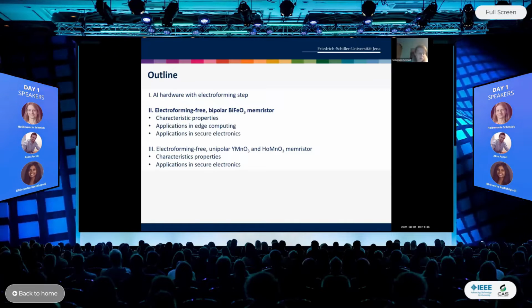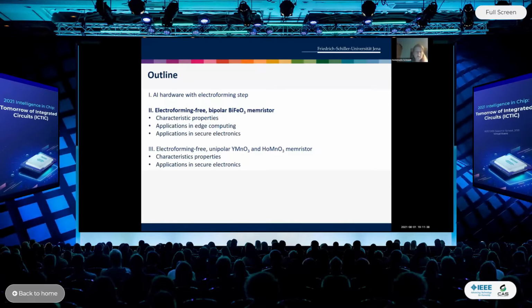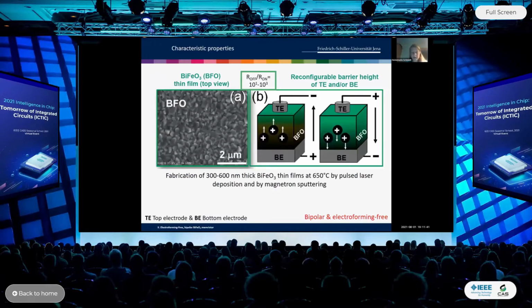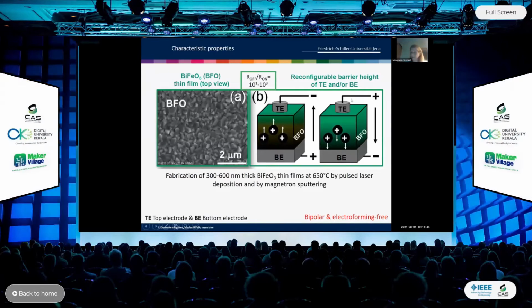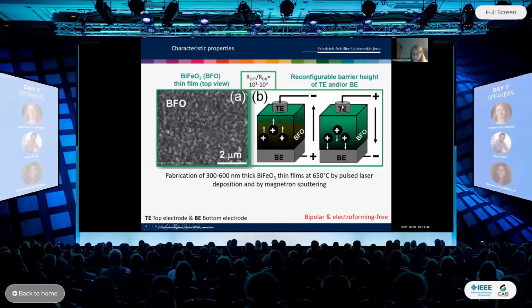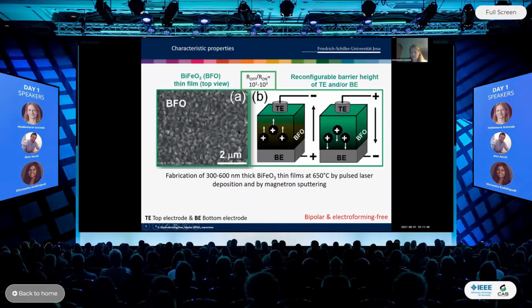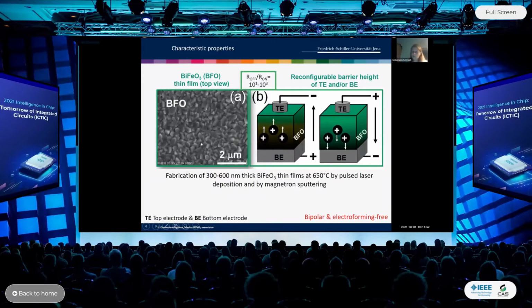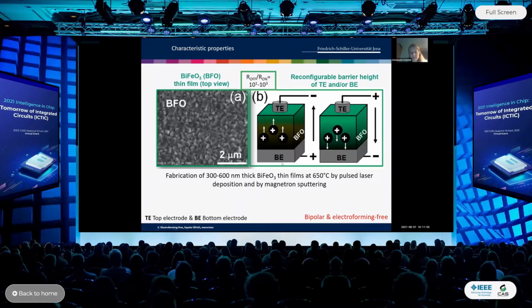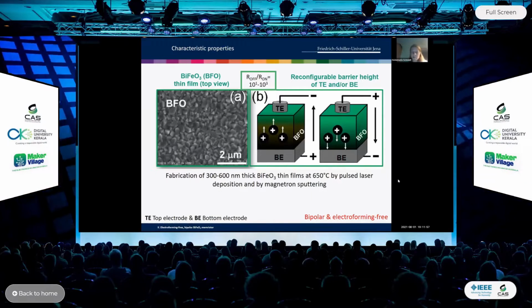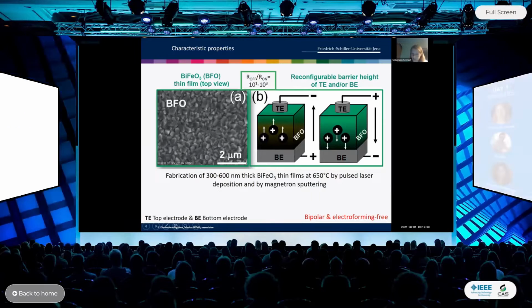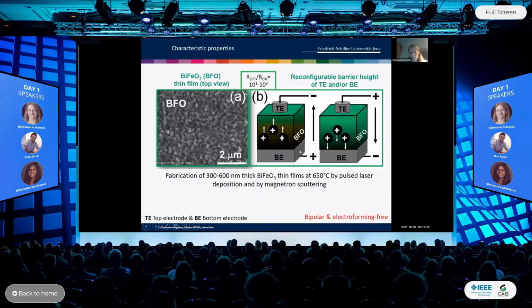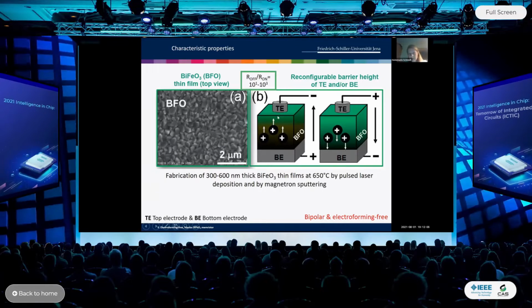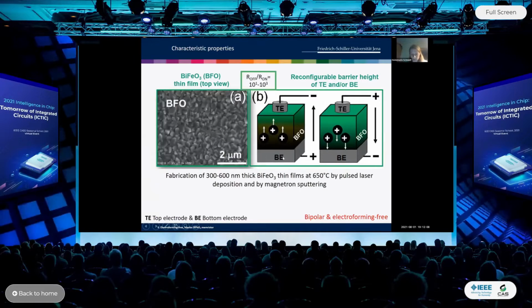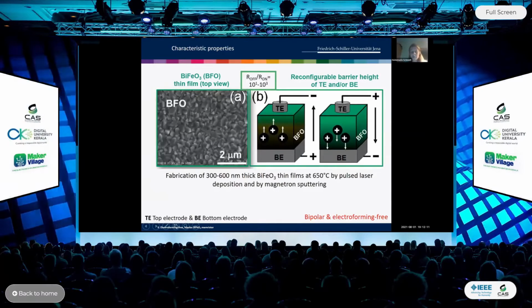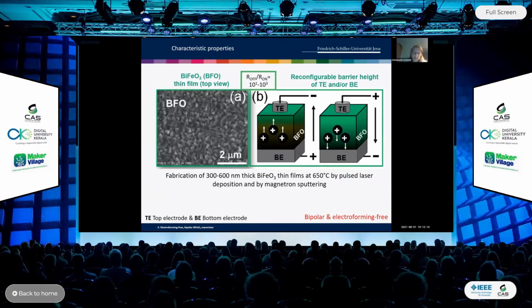And this brings us to the first example of the first part, electroforming-free memristors. This is the bismuth iron oxide memristor. The structure is exactly the same. You have a passive device with a top electrode and a bottom electrode, and it's a polycrystalline device. And now comes the difference. Here, the resistive switching is not related to the formation of filaments, but to the reconfiguration of the barrier height of the top electrode and of the bottom electrode. I will explain this in the following in a little more detail.